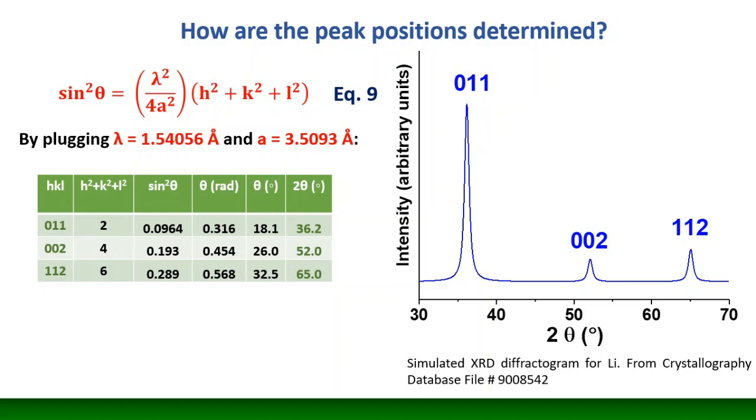We have an example here of how to apply equation 9, okay? For this calculation, we fix lambda equal to 1.54056 angstroms, which, as I told previously, is the wavelength produced by a copper K-alpha X-ray source, and the lattice parameter equal to 3.5093 angstroms, which is the lattice parameter for lithium, according to the Crystallography Open Database file we used to simulate this pattern, okay? So we took hkl equal to 011, then that's going to give a summation of the squares